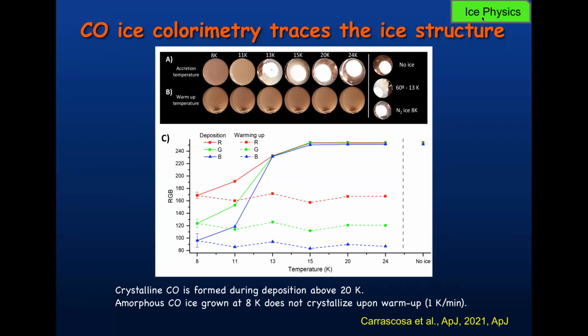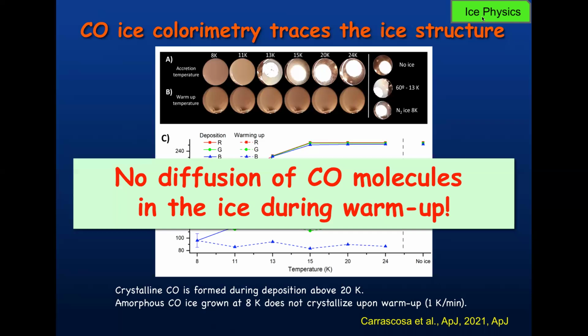So I like this result a lot because you see by eye, just looking into the chamber, the crystallization process of the ice and at which temperature it is occurring. And also you see that pure CO ice is brown. So if you think that brown is related to organics in some moon, be careful because it could simply be some pure ice. It also tells you that diffusion is not important when you warm up the ice. So the molecules, in the case of CO ice at least, don't get enough mobility to rearrange, making an ordered ice. But if you grow it at high temperatures, directly you are making crystalline ice. Okay.